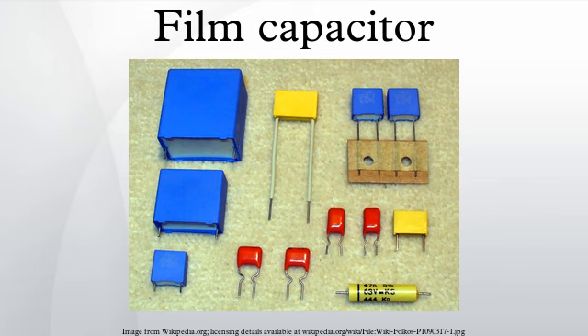A non-catastrophic failure mode in this application is due to the corona effect. The air enclosed in the winding element becomes ionized and consequently more conductive, allowing partial discharges on the metallized surface of the film, which causes local vaporization of the metallization. This occurs repeatedly, and can cause significant loss of capacitance over 1 or 2 years. International standard IEC 60384-14 specifies a limit of 10% C decay per 1,000 test hours. Some capacitors are designed to minimize this effect.